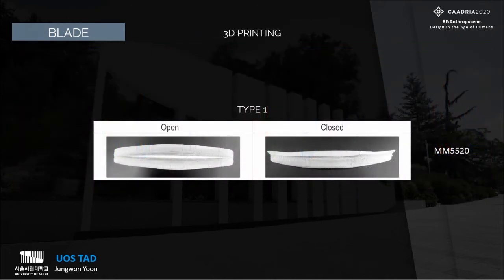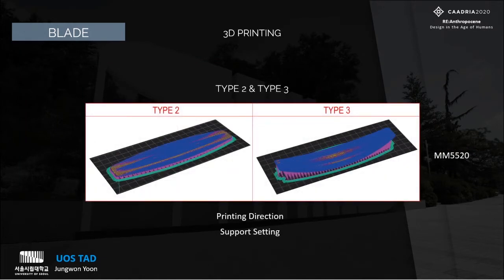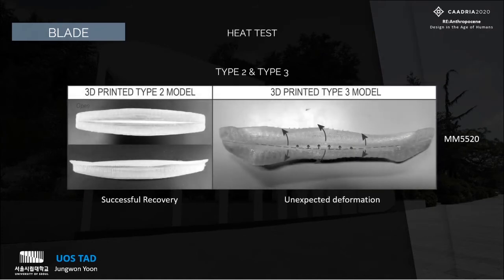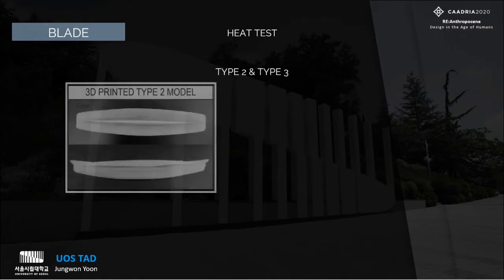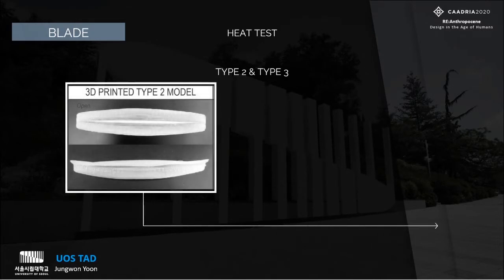You can see the picture of a Type 1 model made of MM5520. In 3D printing Type 2 and 3, printing direction and support setting were important factors determined for successful fabrication. It took 1 hour and 20 minutes for Type 2 and 4 hours for Type 3 to complete the 3D printing. In the heat test, Type 2 showed the successful transition between programming and shape changing. However, Type 3 showed problems in recovering the shape. Therefore, for the further 3D printing test in MM5520, Type 2 was selected. The table shows the different 3D printing settings as per the glass transition temperature.